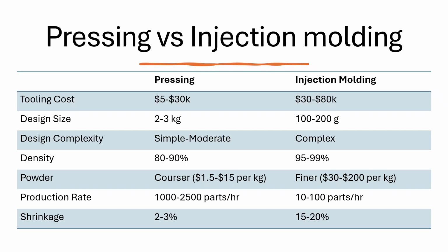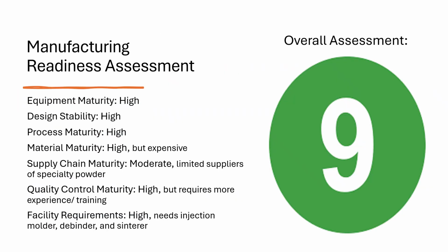The shrinking in the press process is also 2 to 3%, whereas in injection molding, it can be 15 to 20% on the sintering step. This means that there's significantly more consideration that needs to go into designing for injection molding to accommodate this shrinkage. Manufacturing readiness of injection molding is pretty good because the process has existed since the 1980s. So the process has been proven and the equipment is currently commercially available.